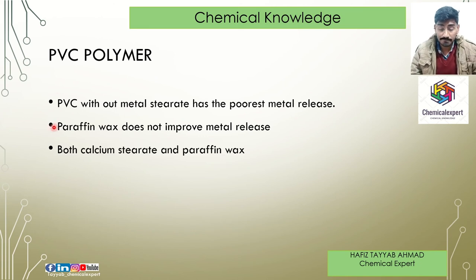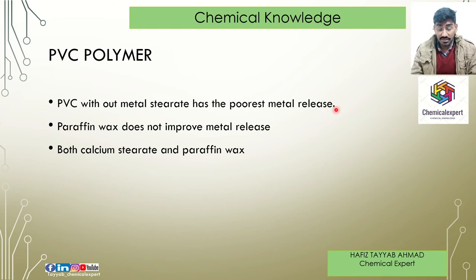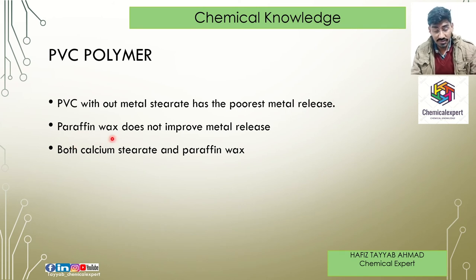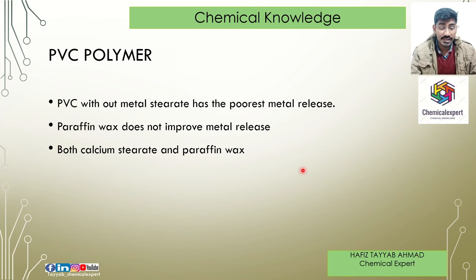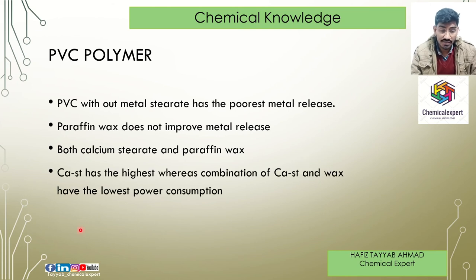Another important factor: PVC without metal stearate has the poorest metal release — metal does not release very well. Paraffin wax alone also does not improve metal releasing ability. However, when calcium stearate and paraffin wax are used together, metal release during extrusion is achieved effectively.